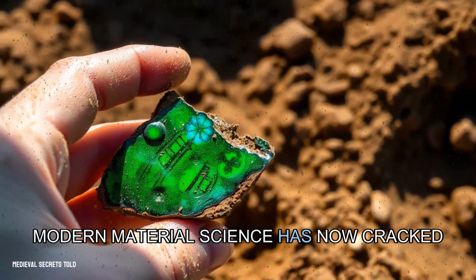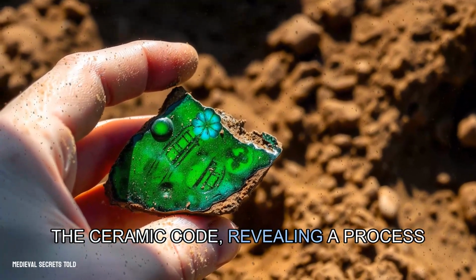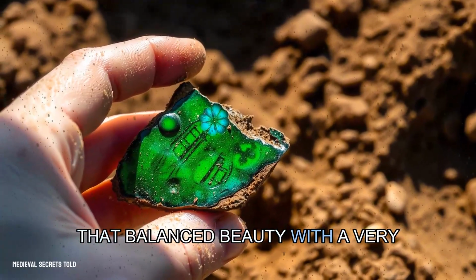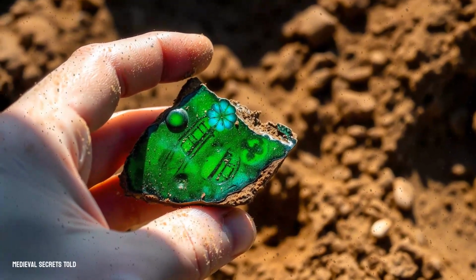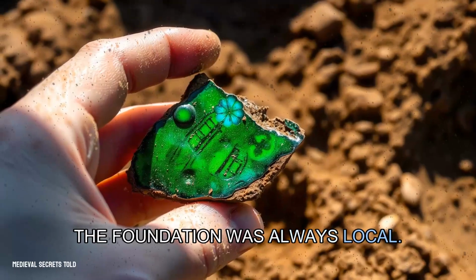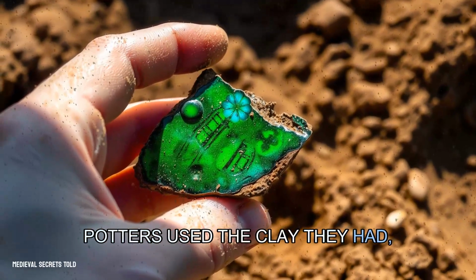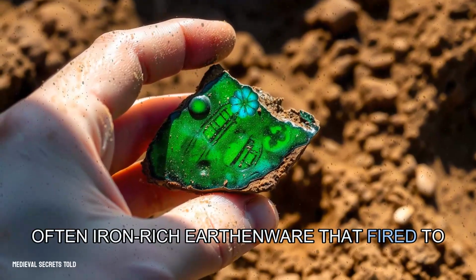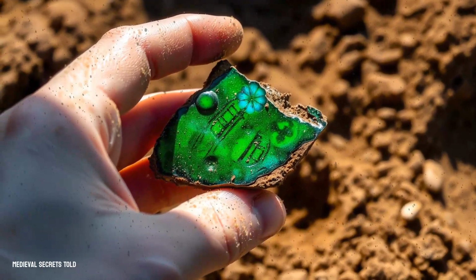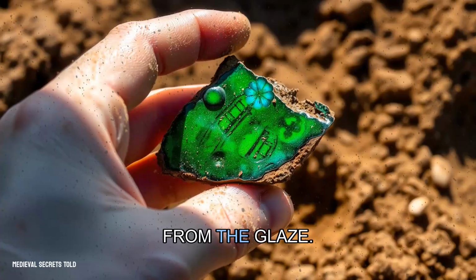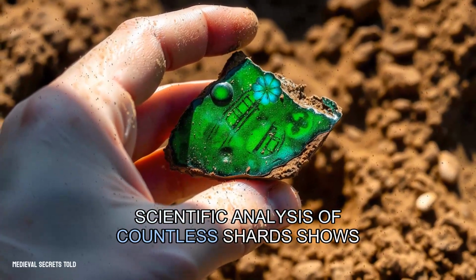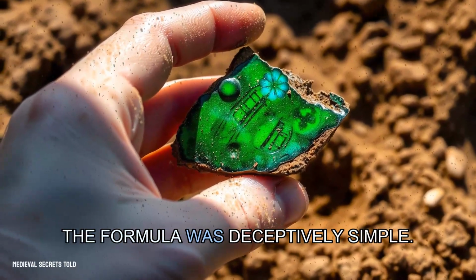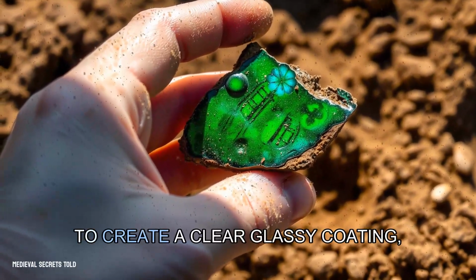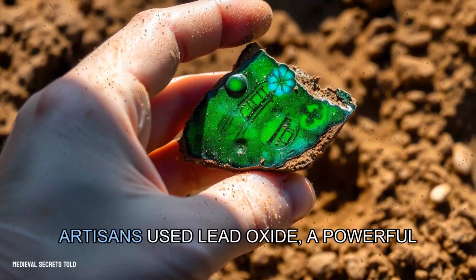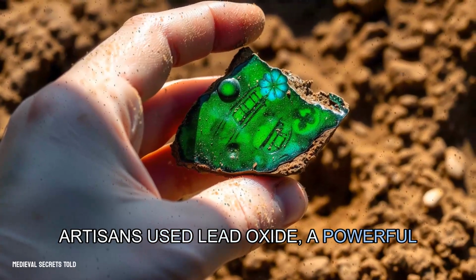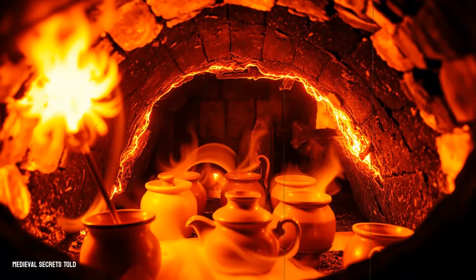Modern materials science has now cracked the ceramic code, revealing a process that balanced beauty with a very real toxic risk. The foundation was always local. Potters used the clay they had, often iron-rich earthenware that fired to a reddish brown. The magic and the peril came from the glaze. Scientific analysis of countless shards shows the formula was deceptively simple. To create a clear, glassy coating, artisans used lead oxide, a powerful flux that melted at a relatively low temperature.